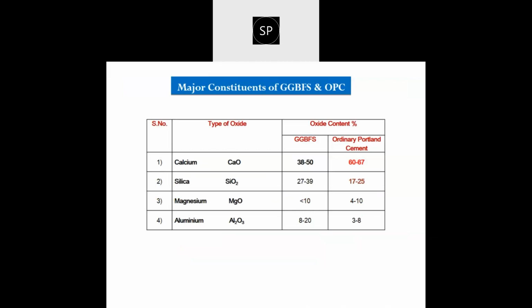In terms of the chemical composition, the GGBFS contains 38 to 50% calcium oxide, while the OPC contains 60 to 67% calcium oxide. The silica content in the GGBFS is normally 27 to 39%, while in the OPC it is between 17 to 25%. Magnesium oxide is normally less than 10%, while in OPC it is between 4 to 10%. Alumina is between 8 to 20% in ground granulated blast furnace slag, while in OPC it is between 3 to 8%. So in terms of the major chemical composition, it is more or less similar to the OPC composition, and therefore it shows very good cementitious properties, and it can be used as a replacement of cement.